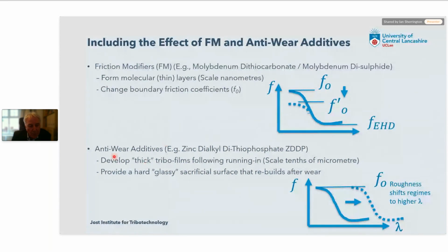In the case of anti-wear additives, the way that they work is they produce this kind of thick-ish sacrificial film on a surface, which is continually deposited and worn off again to protect the surface from wear. And as that happens, it makes the surface somewhat rougher. So it's equivalent to sliding the Stribeck curve to the right of this graph. We can take account of both of these effects in our model.